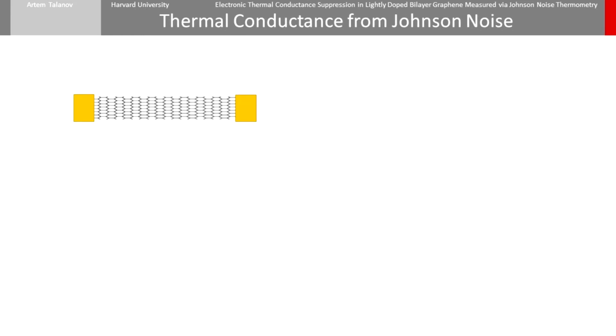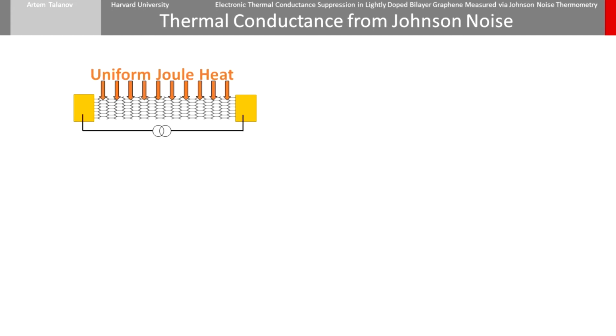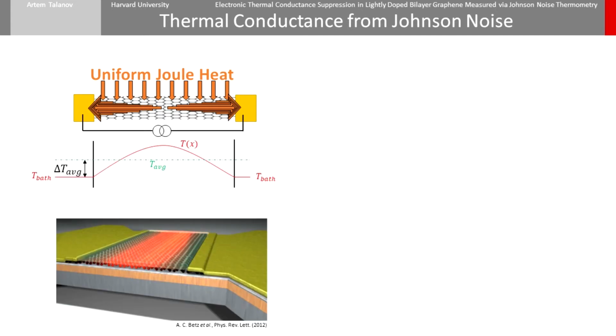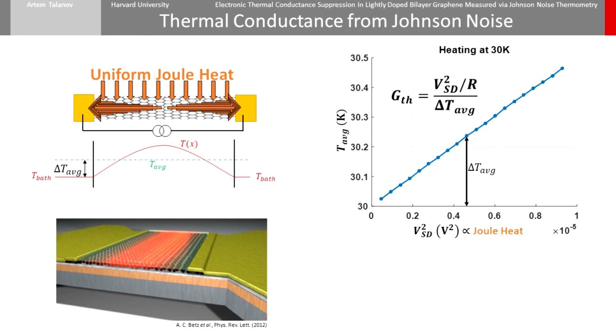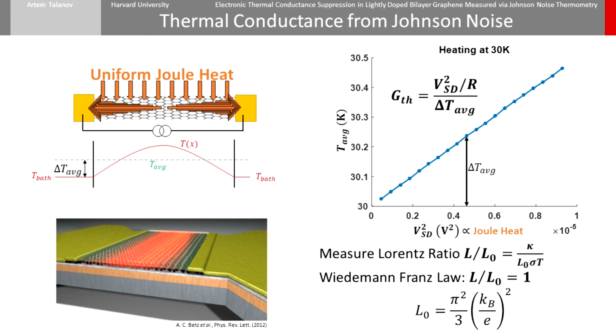How do we actually measure the thermal conductance? We use our so-called self-heating technique. We pass a current through our graphene device, creating uniform Joule heat. This heat diffuses via electronic diffusion to the contacts, which act as a boundary condition at the base temperature. The resulting temperature profile in the device channel is parabolic. Our noise thermometer measures the spatially averaged temperature rise in the channel, and the thermal conductance is the ratio of the Joule power to the temperature rise.